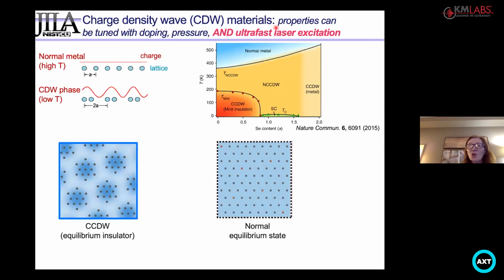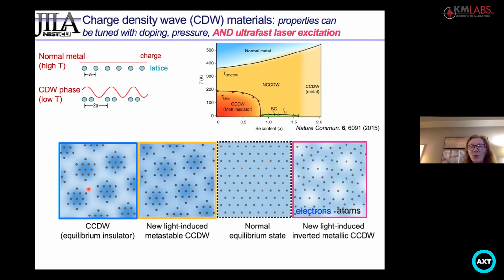So in charge density wave materials, the previous understanding was these were materials that in their normal or melted phase, the electrons and atoms are uniformly distributed, but at lower temperatures, the system can undergo a phase transition to a charge density ordered phase, become insulating, where both the charge, the electrons, and the atoms have relaxed into this state here on the left. Using ultrafast ARPES, we actually found two new phases, a new light-induced metastable charge density wave order and an inverted metallic charge density wave order.